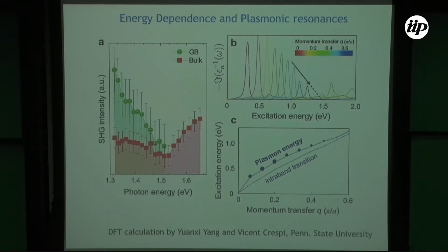So now that we can see the grain boundaries, the second harmonic emission from the grain boundaries, we can study it. Basically what we have done is to measure the second harmonic intensity as a function of the photon energy by using this dark field second harmonic method. In red here is shown the second harmonic emission from the bulk part, where there is no grain boundary, and in green here is the second harmonic emission intensity from the grain boundary.